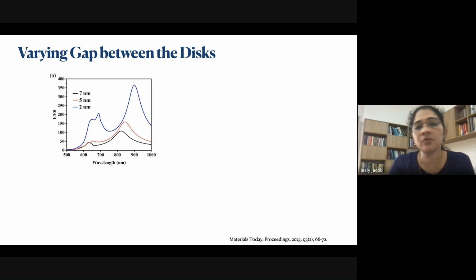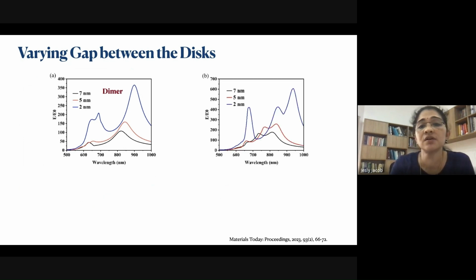So now we are optimizing it a little more, testing it by varying the gap between the discs. You can see here, first we have taken a dimer and the gap size is decreased. You can see here when the gap size is decreased from 7 nanometer to 2 nanometer, the field enhancement is improved. Also, more hotspots are visible.